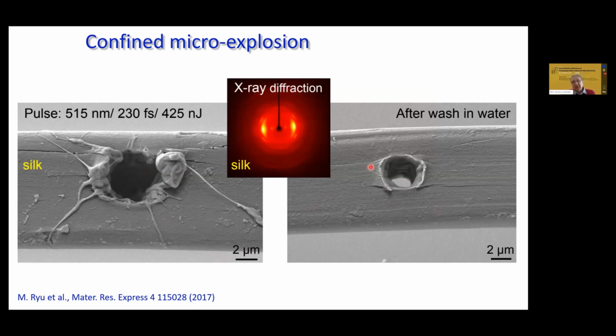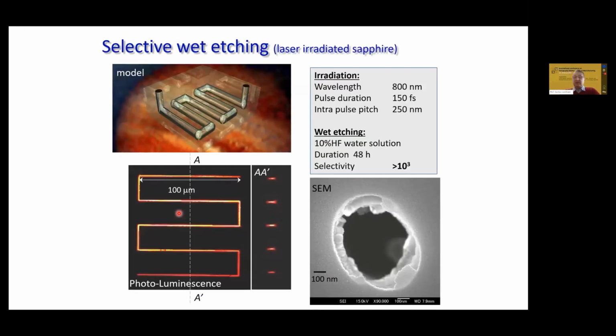Silk is a crystalline material. You see it here by diffraction pattern. It shows crystalline features. And a single pulse is creating, obviously, an ablation spot, but the material around can be washed out in water. And this is unusual because silk, if you modify it by temperature, is usually polycrystalline, and silk is not easy to wash. So you need amorphous, which is quenched very, very fast, to be able to have it water soluble. So it's another example of very fast quenching and capturing an unusual state of material in the laser illuminated spot.